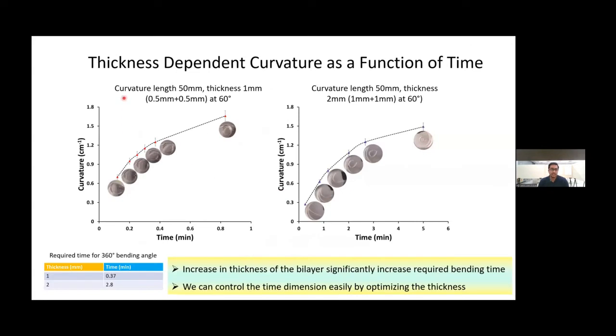Here is the thickness dependent curvature formation. We have found that with increasing thickness, the actuation speed or bending time also increases. With increasing the thickness, the bending time also increases.